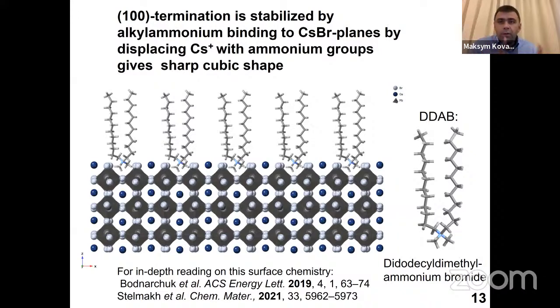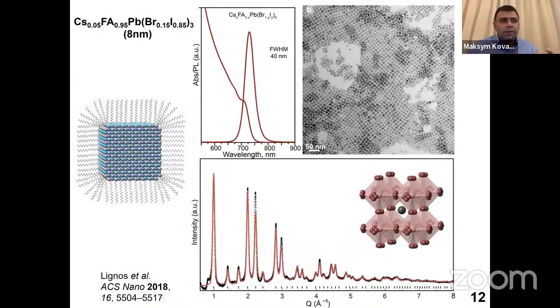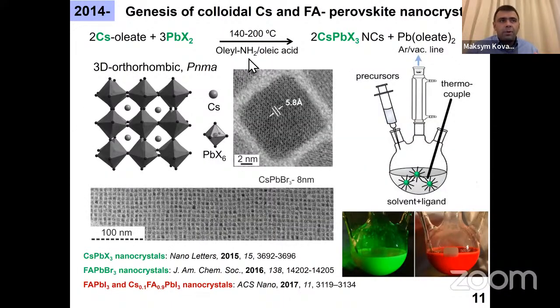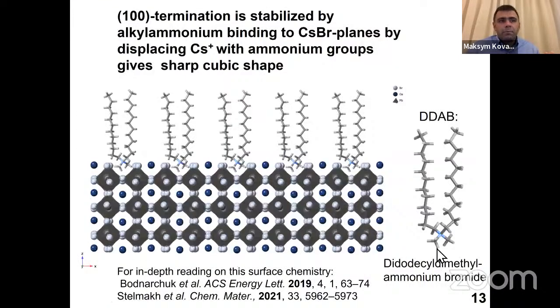And so in our first synthesis, as you might recall from this slide before, we used primary amine, which converts into ammonium, a long chain alkyl ammonium capping ligand. Another example is shown on this slide, which is dialkyl ammonium. So this is an ammonium group, which is positively charged, and two alkyl chains.